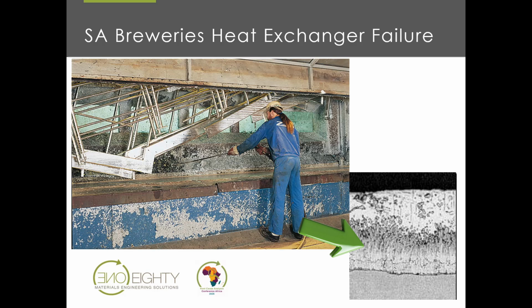And what's important to know about galvanizing that many people don't know is that it's a metallurgical bond. There's actually an iron-rich layer over here, and a low level of zinc. And as you move from this layer to that layer, you get an increase in zinc and a decrease in iron. And each of these little phases in the zinc coating need to be present for the zinc coating to be effective. If the zinc coating doesn't form and look like that, the zinc coating will not be effective.